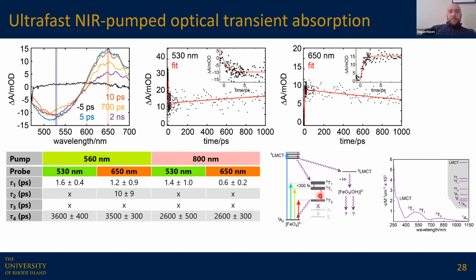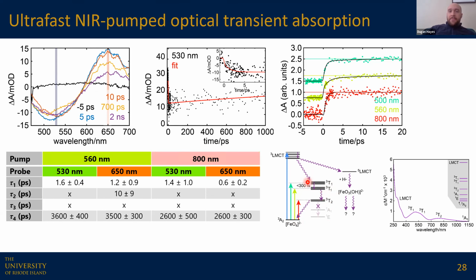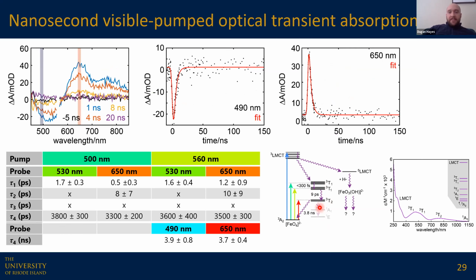We can also compare what we see following visible absorption and near infrared absorption directly into this triplet T2 manifold that's fairly well separated from these triplet T1s. And then we actually do see a difference where we get this instantaneous growth when we pump at 800 nanometers, with the slower component that we see when we pump in the visible. And so we're assigning that to the relaxation to this triplet T2. And so putting all this together now, we can complete the photophysical relaxation branch.